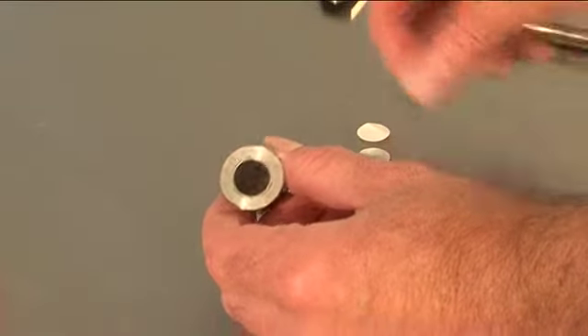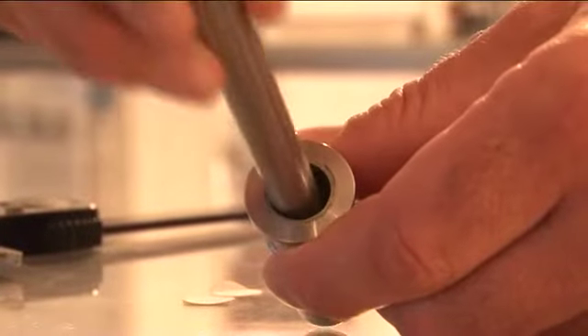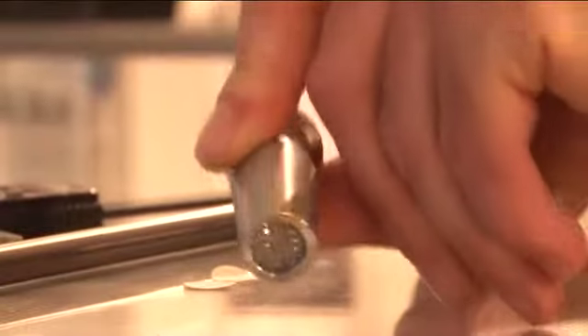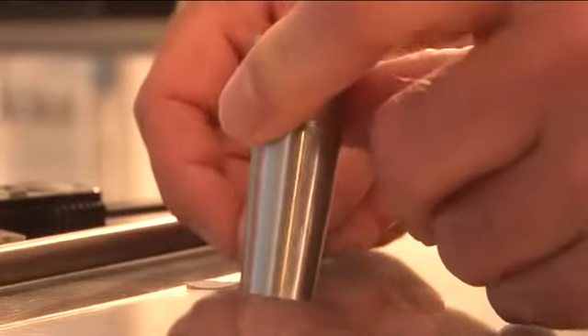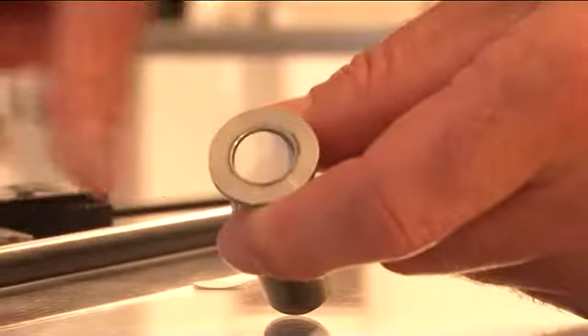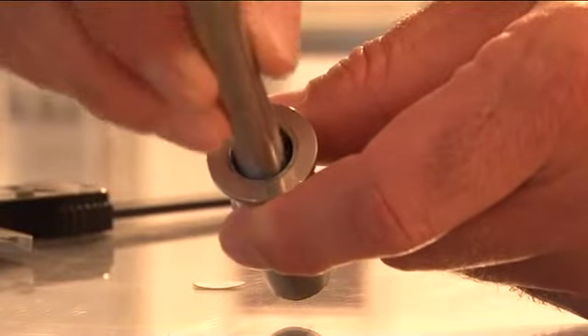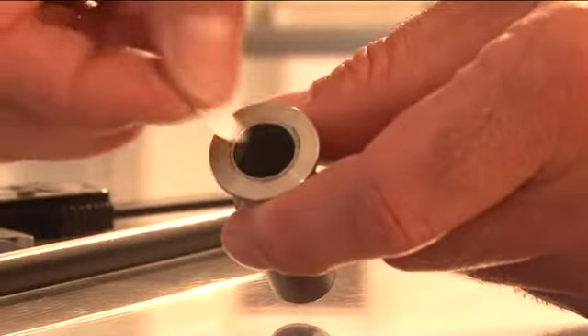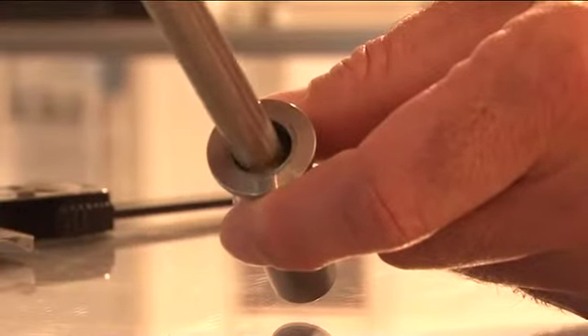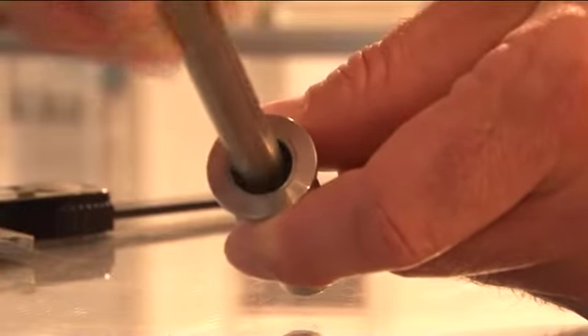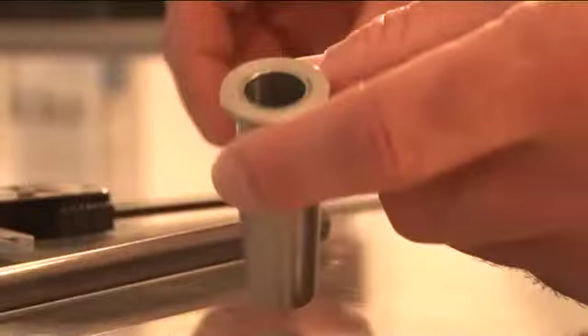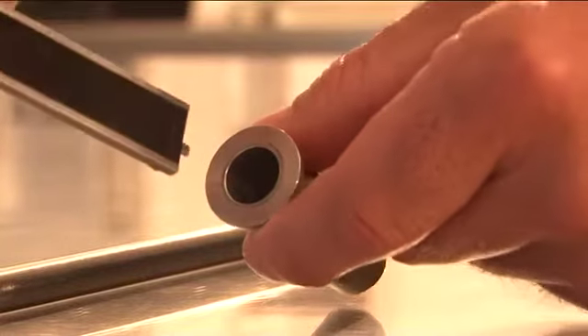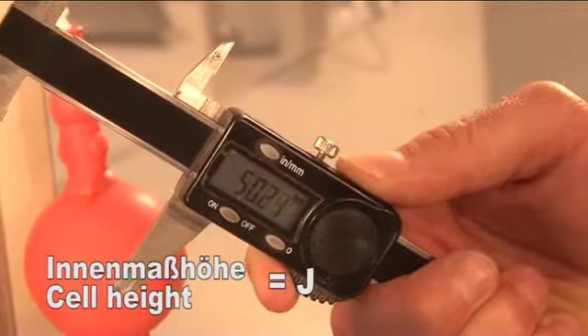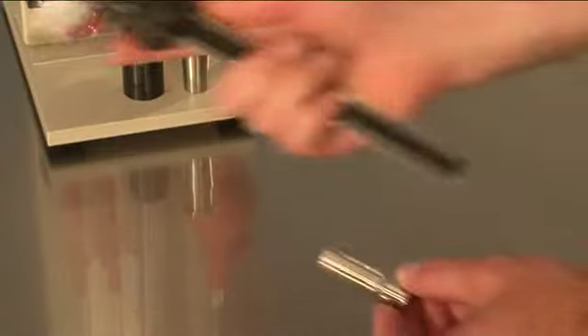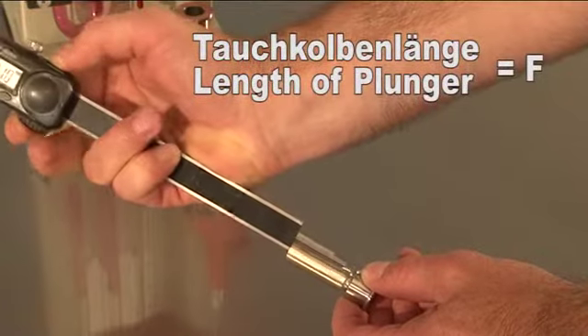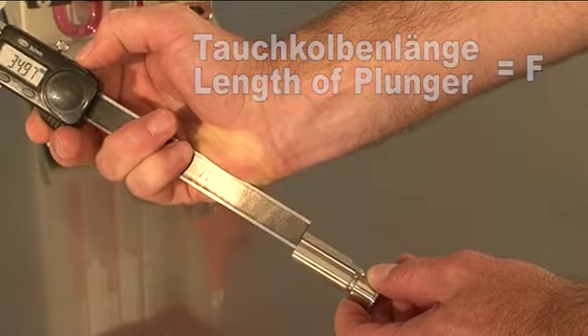The perforated disc is placed on the lower edge of the measuring cell and pressed in with a tamper. 2 filter paper discs are inserted and pressed with the tamper up to the stop. Now, using the depth gauge, measure the inner dimensions J of the cell at 6 different points. The measurement should be accurate to 0.01 mm to give an average value. Also, measure and determine the length of plunger F at 6 points.